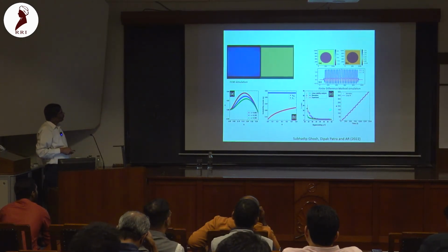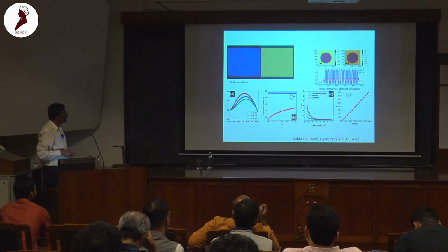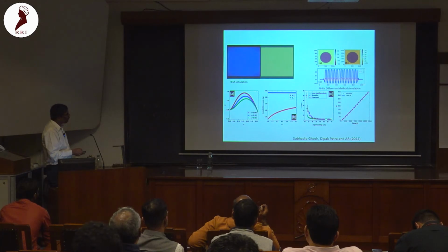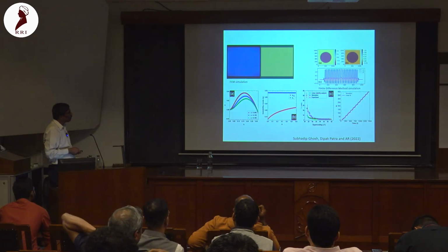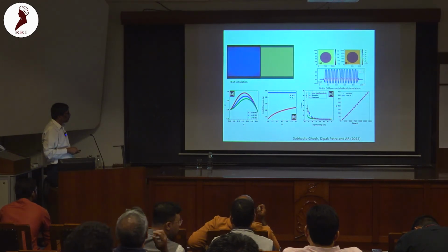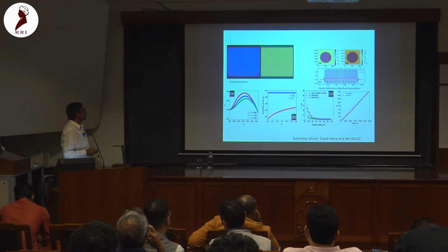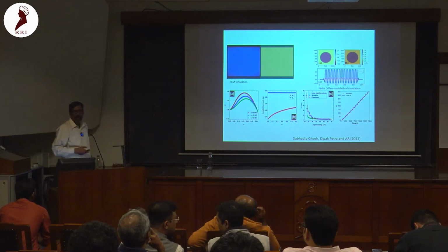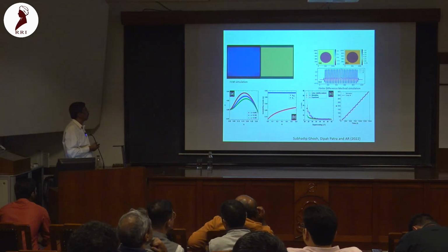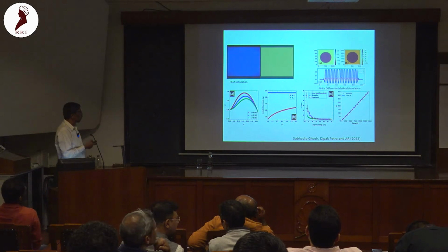And we used the linear stability analysis as well as the simulation values. We also measured the periodicity of these bands at different supercooling. And the theory and experiment seem to match. So we believe that this is a reasonable explanation of the banded spherulitic growth in our system.